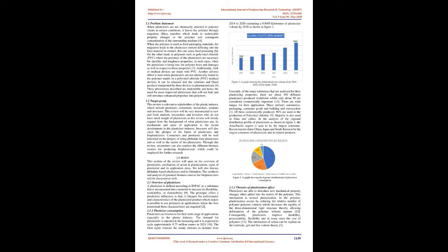On the other hand, in polymers such as polyvinyl chloride, PVC, where the presence of the plasticizers is necessary for ductility and toughness properties, when the plasticizer is being lost, the polymer loses those properties as well. Additionally, the bulk of medical devices are made with PVC. Another adverse effect is seen when plasticizers are not chemically bound to the polymer matrix in PVC medical devices. It can be released into the solutions and blood products transported by these devices in pharmaceuticals. These phenomena described are undesirable, and hence the need for more improved plasticizers that will not leak and still introduce enhanced properties into polymers.